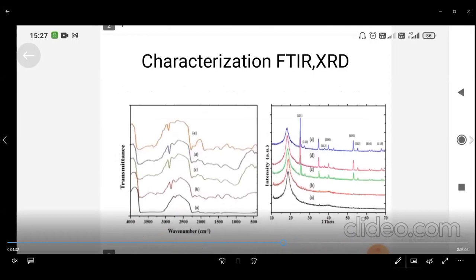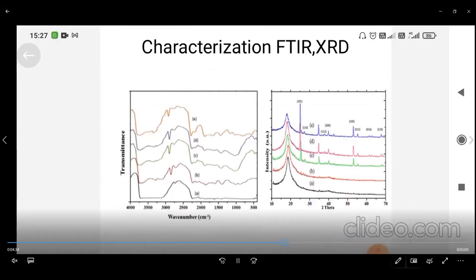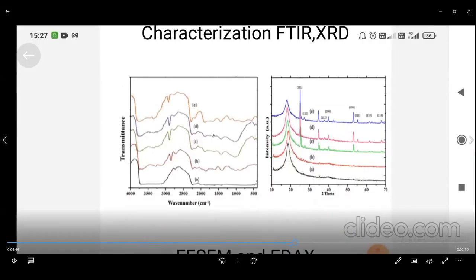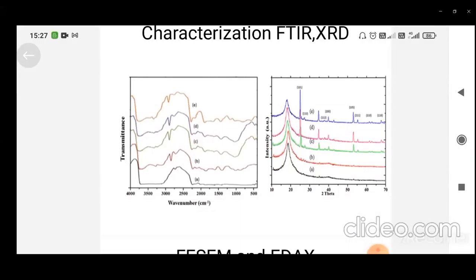By studying the dielectric modulus and impedance spectra of the composite, the relaxation mechanism was explained. The good formation of polyvinyl alcohol TiO2 composites is confirmed by structural analysis like XRD, FTIR, and SEM with EDX analysis. The study of XRD revealed the presence of both rutile and anatase TiO2 in the composite. The porous nature of the film at 30% concentration of TiO2 was observed, as shown in the figure. It is also observed in SEM.